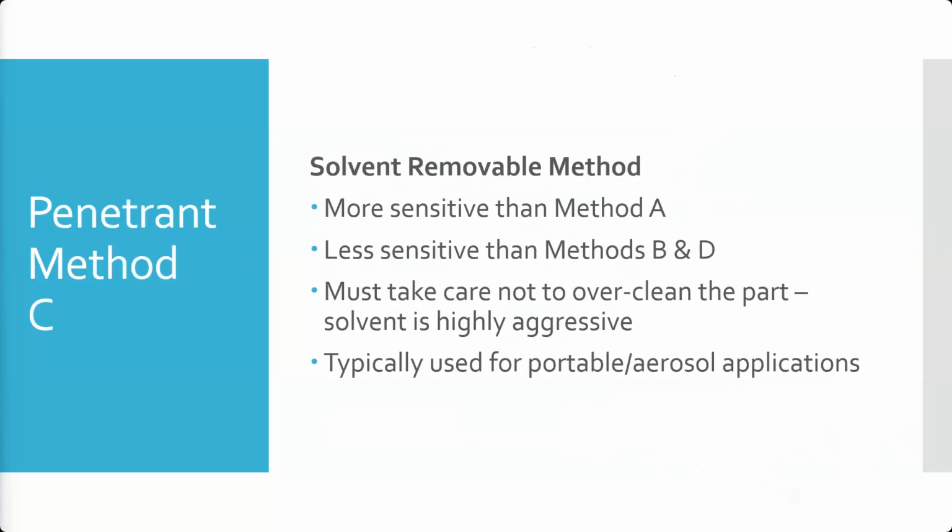This, however, is probably the most common method we use simply because it is portable. It's able to be done in a portable and aerosol setting. And so for in-service inspections on parts that are either installed on aircraft, or if you're outside of aviation, items that are installed in a production line or on a pipeline or any other application like that, it lends itself to those kinds of applications versus something like the water washable or methods B and D, the lipophilic or the emulsifiables, post-emulsifiables.